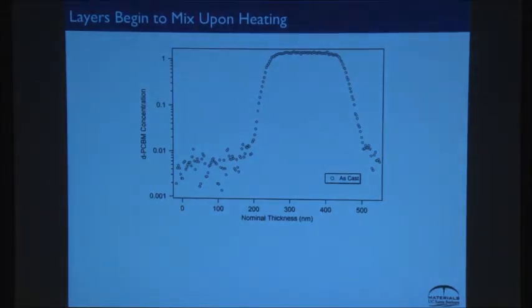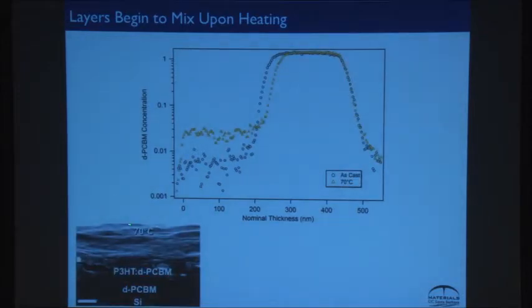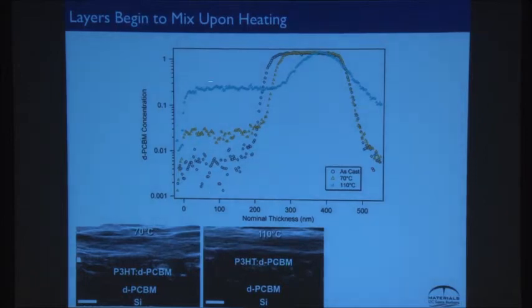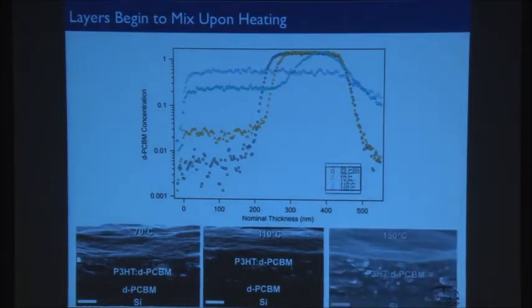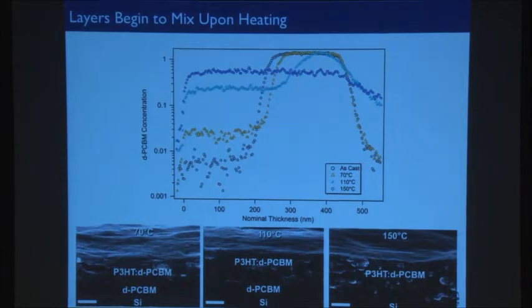And when we first did this, it was quite surprising because everyone said, well, they're not miscible. But we heat up at low temperatures, much lower than the 150 C that people use. And suddenly we start seeing some deuterium in what is the polymer region. We heat it up some more, and then we see a lot more fullerene. And then we heat it up some more, at the temperature everyone uses, and it's uniform. It's all fully mixed. Okay?